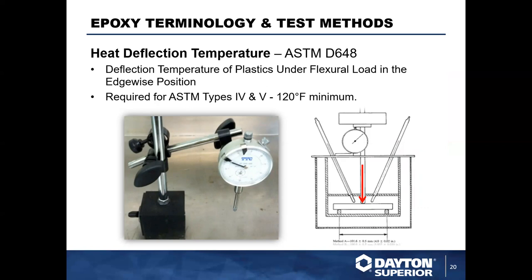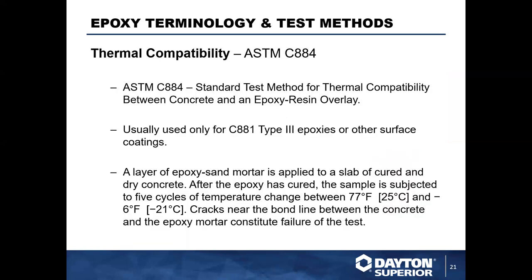Heat deflection measures the temperature at which a plastic deflects under a flexural load. Types 4 and 5 typically require a minimum of 120°F. Thermal compatibility is addressed by ASTM C884, the standard test method for thermal compatibility between concrete and epoxy resin overlay — this is typically only relevant when using Type 3 epoxy overlays.